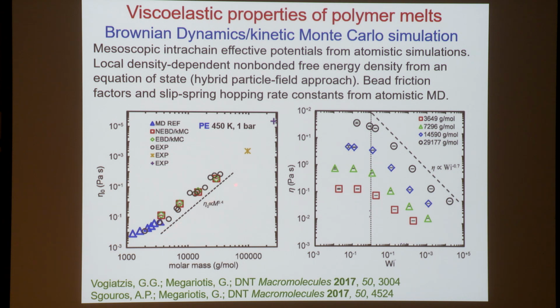And overall, we're quite happy that these results are consistent with the scaling of the zero shear viscosity with molecular weight, that for long molecular weights in the entangled regime, eta 0 goes like molecular weight to the 3.4 power. Down here, you can see also results from atomistic molecular dynamics with the blue triangles. Necessarily, they are confined to small molar masses because the relaxation times are manageable by molecular dynamics only there, along with the experimental measurements.